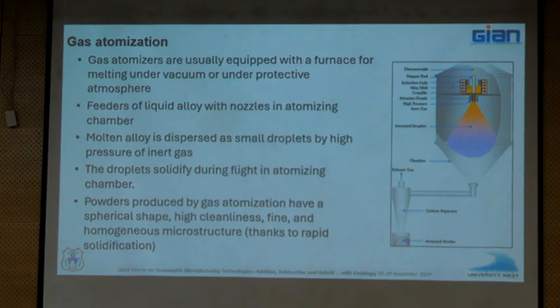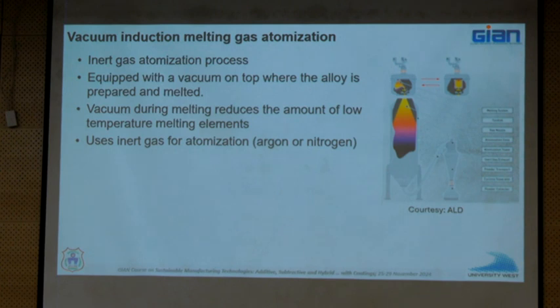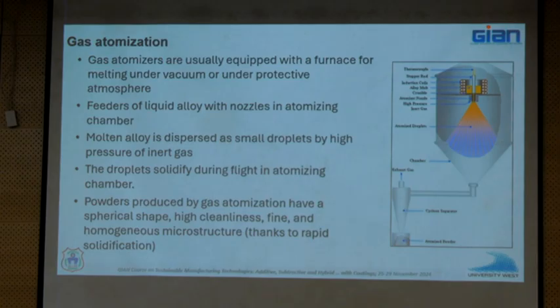Even homogeneity from a chemistry standpoint is assured, because you're just melting that stream and solidifying that. So there is no in situ reaction involved or any such thing. So you get a very homogeneous microstructure as well because of the rapid solidification. Yeah, and there are some different variants of this gas atomization, but most of the differences essentially come there, right? How do you melt this? All the difference happens there.